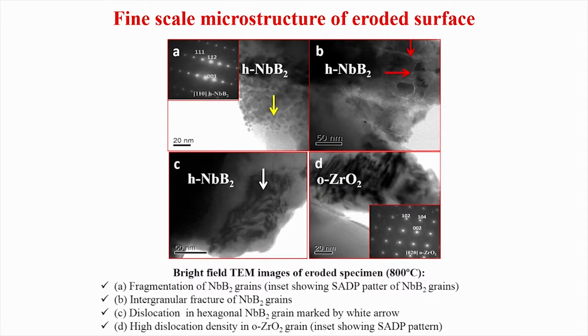Now, what we have done, and that is quite interesting, is that we wanted to understand the wear mechanisms with much more clarity. In order to do that, we took the eroded surface and the debris particles, and did very careful TEM sample preparation: we put it on the grid, milled it, and then took transmission electron microscopy images. What you see is that in most cases there is niobium boride, but there is also orthorhombic zirconia. This orthorhombic zirconia was not present initially, it was all tetragonal zirconia.